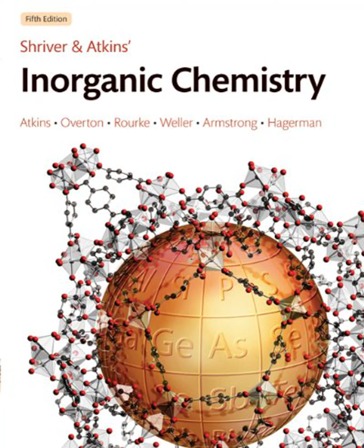So what makes a solid good at conducting ions? Well, for cationic electrolytes where positive ions move, like the silver in Ag2HgI4, what often happens is that at higher temperatures, the cations get disordered. They spread out over many possible sites. So in Ag2HgI4, above 50 degrees C, there are actually more available sites than silver ions. It's like musical chairs. They can just hop around really easily. Oh, okay. More chairs than players.